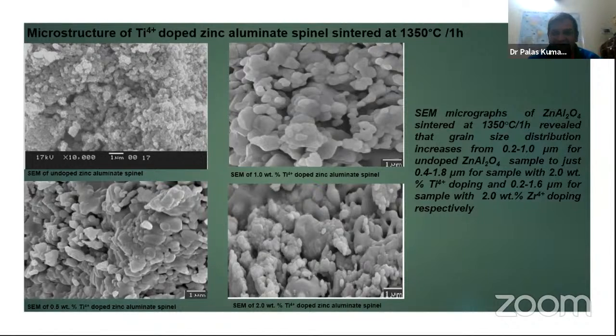And in the same micrograph of zinc aluminate sintered compact, it is revealed that the grain size distribution, if we see the size, increases from 0.2 to 1 micron for undoped, for zirconia 0.4 to 1, for titanium 0.4 to 1.8, and for zirconia-titanium 0.2 to 1.6.